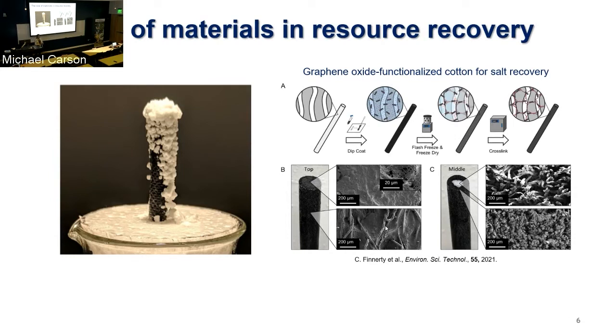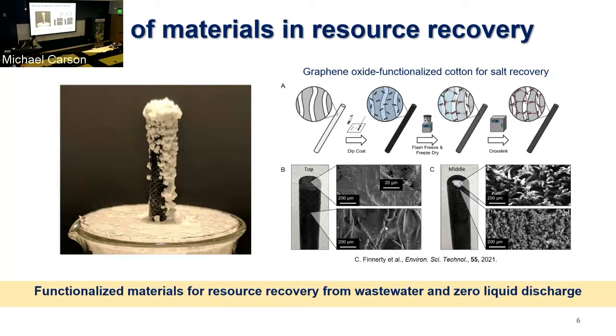So in this case, it used a cotton stick, and the cotton was functionalized with graphene oxide to really give it these solar absorbing properties. But you can see here the graphene oxide really just coats the outer surface. So the inside of the stick still maintains the properties of the cotton, which is what allows it to really pull up the water in order to get evaporation. So we can really use these types of functional materials to get to resource recovery as well.